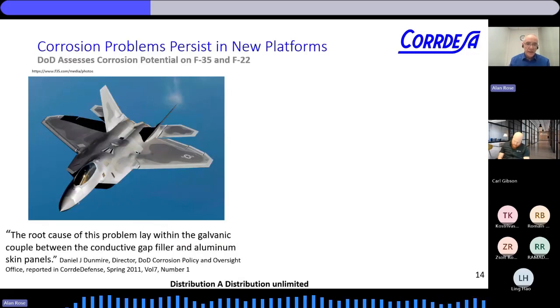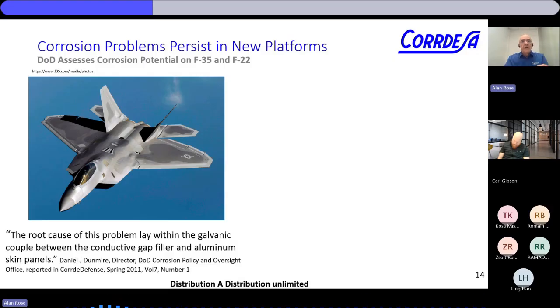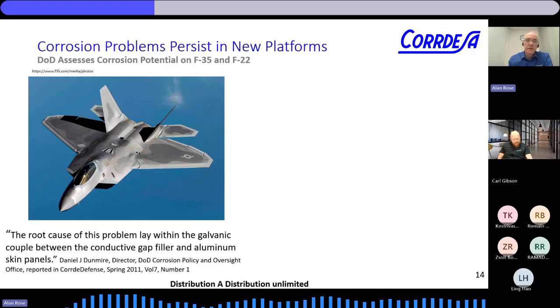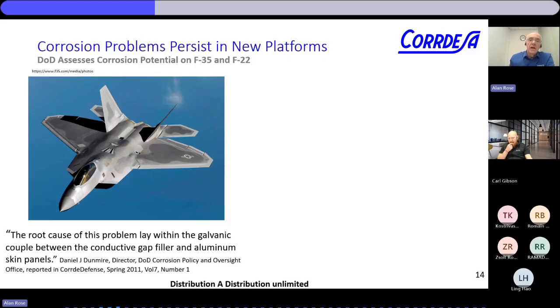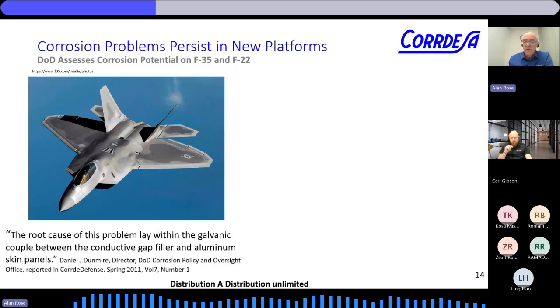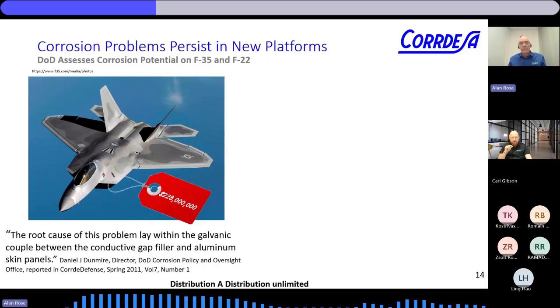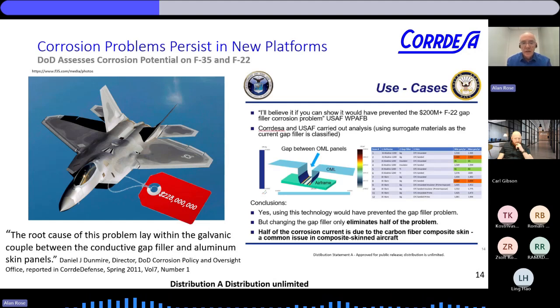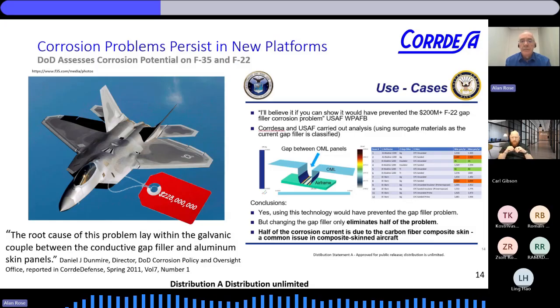So clearly they needed to deal with that. Now the F-18 is quite an old asset, but even the newer assets, there've been issues. There's issues with F-35, but on the F-22, there's quite a well-known issue, and that was a gap filler that they chose on the wing panels. And this conductive gap filler, which was chosen for obviously low observable type of issues, had unexpected impact in the accelerated galvanic corrosion. And just to fix that one problem cost more than $228 million. So clearly, if you have tools up front, you can look at the impact of these choices of materials, see what the impact is on your total design. We've done this retrospectively, and in the software that we developed, this would have flagged up like a Christmas tree, and it would have been a non-event. We would have dealt with it and worked in an alternative material.